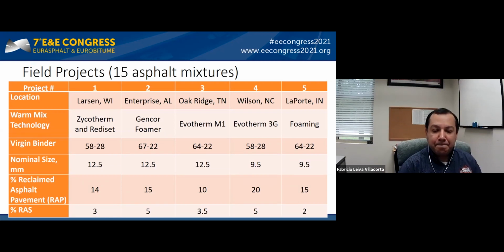Here I'm showing the 5 projects that were selected at different states, one in Wisconsin, the other one in Alabama, Tennessee, North Carolina, and Indiana. And we have a variety of technologies, 3 additive technologies and 2 foaming technologies. We also have a variety of virgin binders ranging from 58-28 all the way up to 67-22. We have different sources from aggregate and sizes ranging from 9.5 millimeter to 12.5 millimeter.